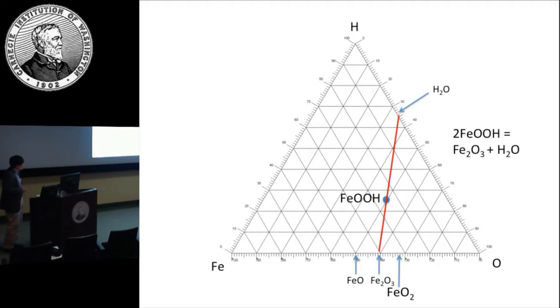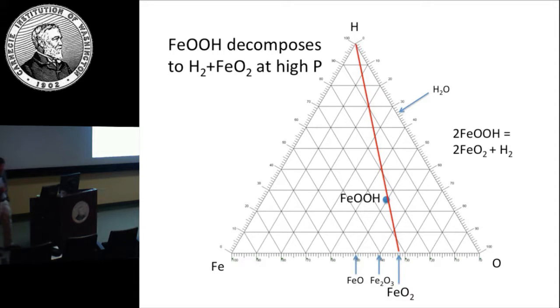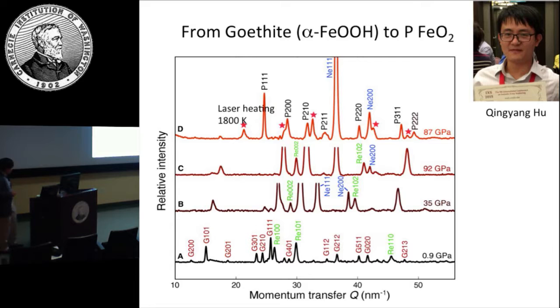Okay, so we ran an experiment starting with this goethite, and at high temperature it decomposes into this. This is the valid phase diagram, and at ambient temperature it is the solid form. So we want to see whether at some point it goes to this. Qin Yang ran this experiment: at low pressure it is goethite, and the goethite stays up there. Then when you go to 80-some GPa and laser heat it, this pyrite structure phase comes out. We put the goethite inside a neon pressure medium to avoid reaction with the other materials. The neon peak is still there, but most of it is the pyrite phase, except for some of the stars, where the epsilon FeOOH is left unreacted.